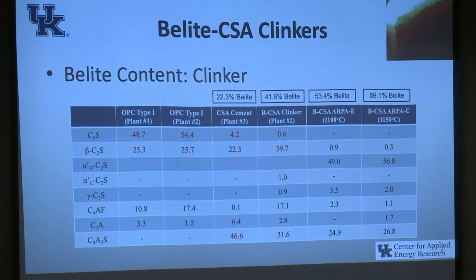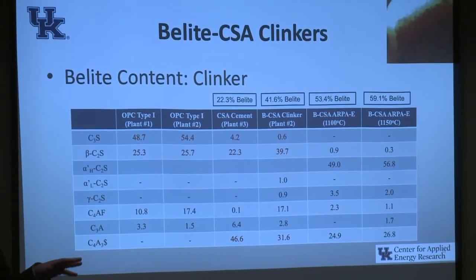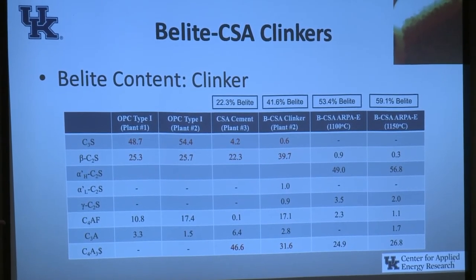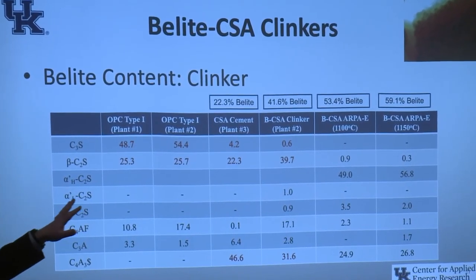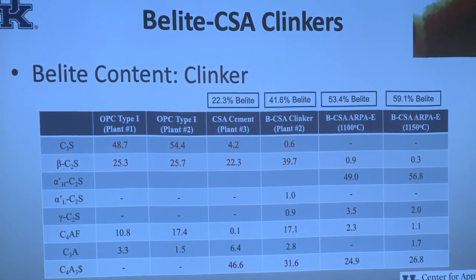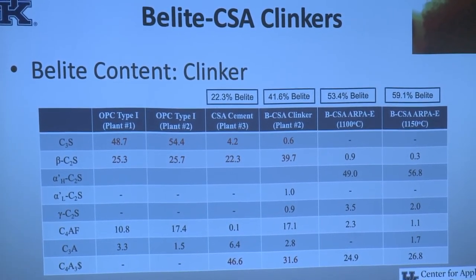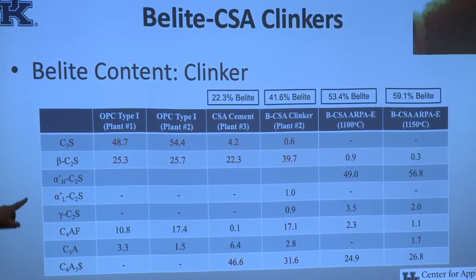So looking at what that breakout is. C2S, this is cement notation, so I apologize to the chemists in the room. Try not to make sense of it. So the beta, alpha, the gamma. But the point is, the far two columns represent the cements we created in the lab for the RPE project. So I had roughly 53 and 59% Belite present, up from a typical commercial CSA plant, which is around 22% Belite. So not much, but it's present. And the 41%, there are some cement plants out there doing industrial test runs of some of these Belite CSA materials, whereas your Portland cement has roughly 25% Belite present, just to give you some difference.